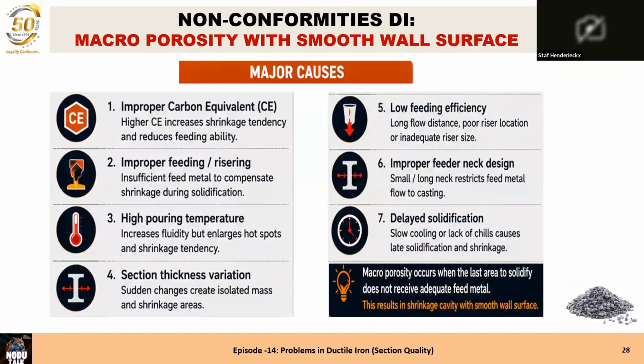Smooth wall is when the carbon equivalent is high. I have the experience that if you have casting sections above, let's say, 25-30 millimeters, and you have a carbon equivalent of 4.5, you will get shrinkage with smooth walls inside the cast. And improper feeding and risering is of course also here, but due to the high carbon equivalent, the feeding is disturbed and will have problems reaching all areas. The temperature again is very important, and the section thickness, of course, creating isolated mass or not.